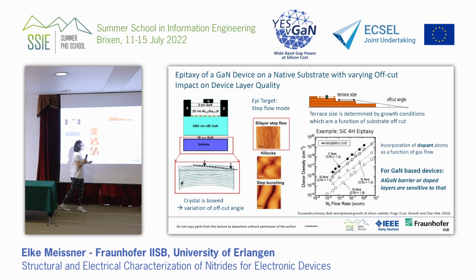And you see, for example, how the epitaxial conditions are influenced by the properties of the terrace size. The size of the terrace determines your growth process, and what the consequence is if you want, for example, to incorporate dopants, or in this case, to grow an aluminum gallium nitride layer, which is an alloy composition, so at the same time you run two different reactive gases. This is, for example, with a silicon carbide device as an example, showing that the incorporation of dopant atoms also depends on the structural quality of the substrate, because it determines the terrace size.